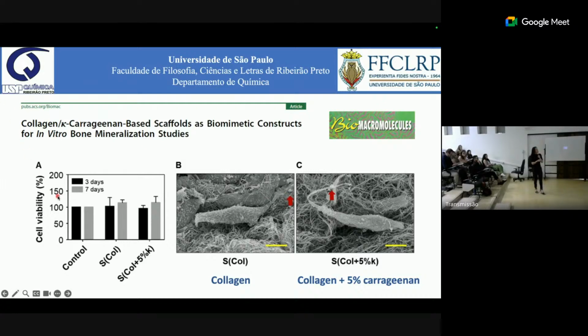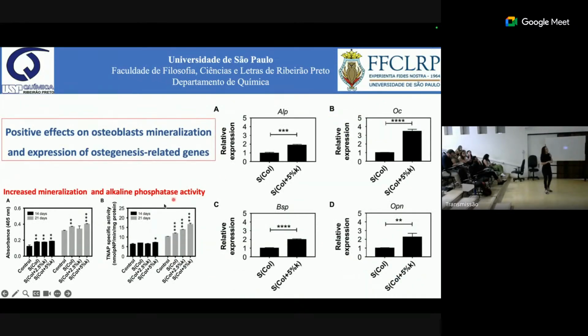So we prepared these collagen kappa carrageenan scaffolds, and we cultivated osteoblasts at the surface of the materials. The scaffolds contain only collagen and collagen carrageenan. We found increased mineralization and increased alkaline phosphatase activity for the osteoblasts in the presence of the scaffolds, especially the scaffolds containing kappa carrageenan.